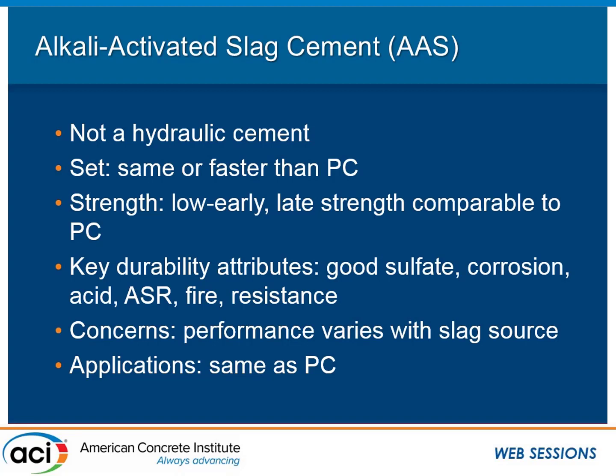One of the other things about alkali-activated cements is that they do require, in many cases, a heat cure. So if you mix it up and set it on a table, nothing's going to happen. But if you put it in the oven for 24 hours, you might get up to 8,000 psi in one day, no problem. So that is kind of a limiting factor right now, but applications like precast could be a good place for that. So again, performance varies.